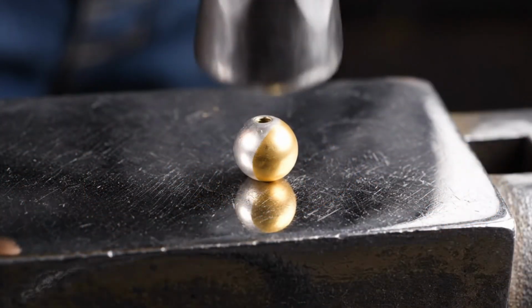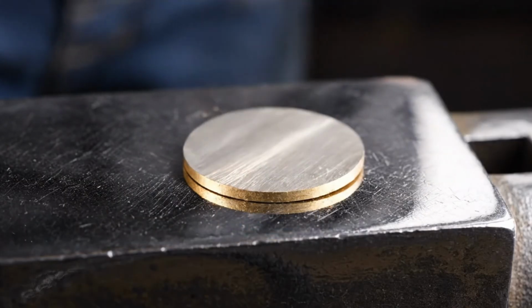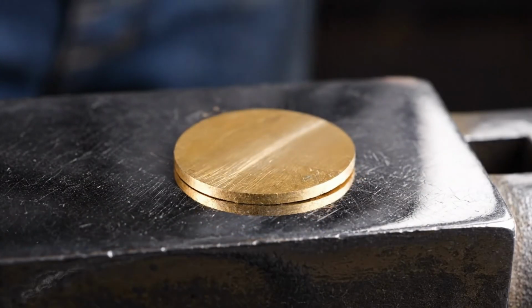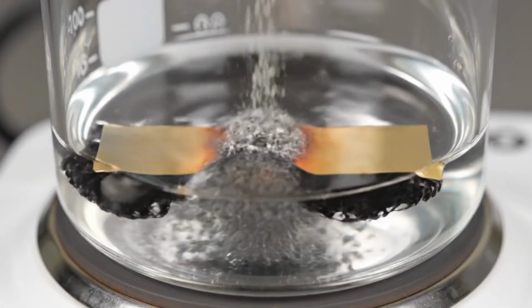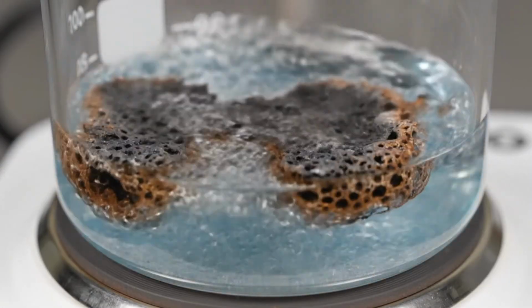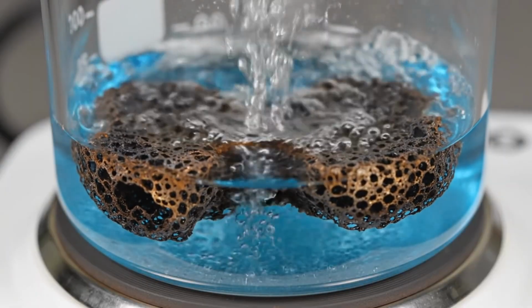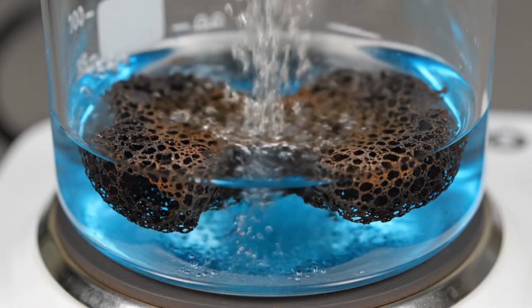What remains is a small bead of gold and silver, which we flatten and roll into a thin strip to maximize its surface area now. This strip is boiled in nitric acid, which dissolves the silver completely, leaving behind a fragile black-colored sponge of pure gold at the beaker bottom.